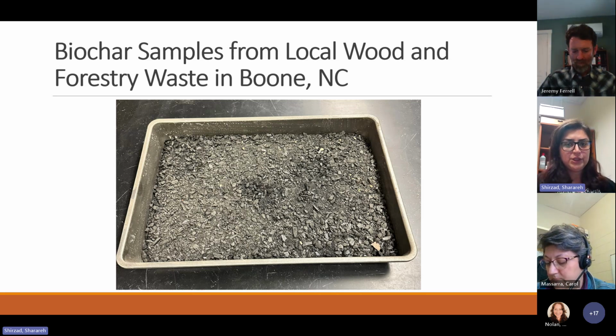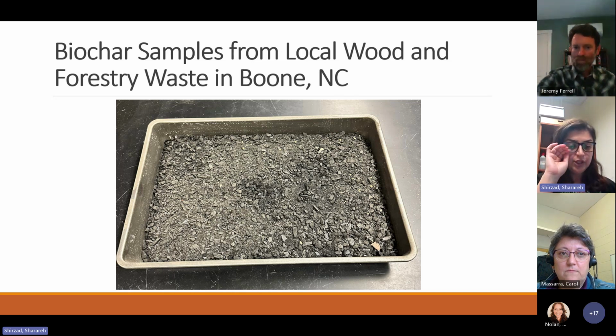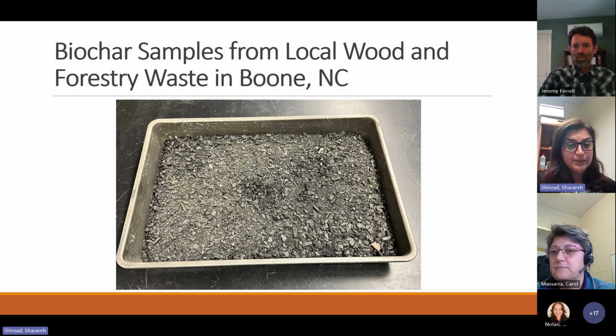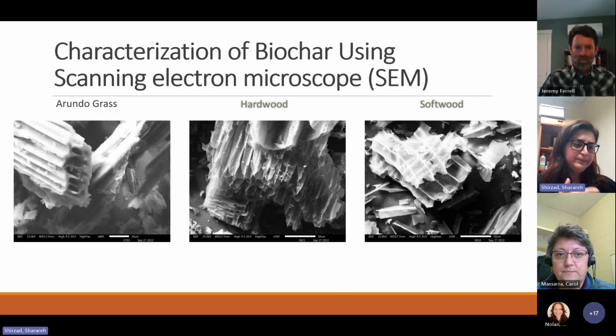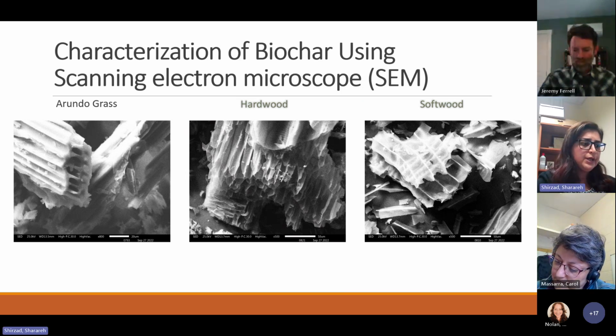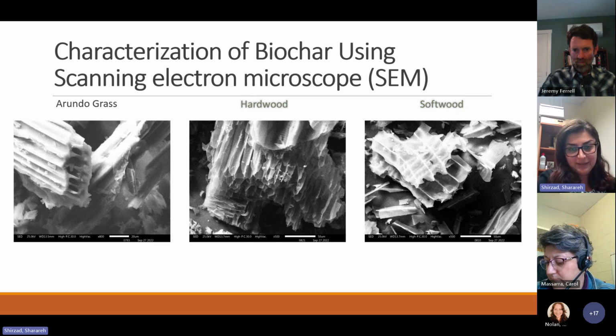in our concrete mixture. So for our project, the first thing that we looked into was the physical and mechanical properties of our biochar. We basically characterized properties of our biochar. We looked into physical properties such as particle size distribution, density of the material, and pH of the material. And we also used scanning electron microscopy to be able to have a better understanding of the structure of these three biochar samples that we have.